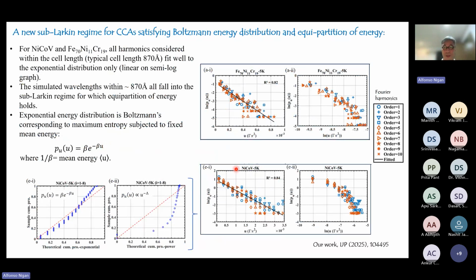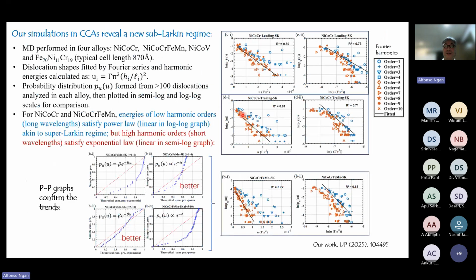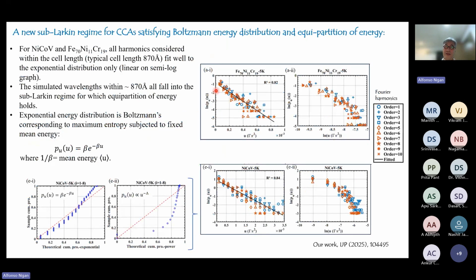And this graph shows the remaining alloys that we have looked at. So these two are that one and that one. For these two alloys, within the length of the simulation cell, we only see the Boltzmann distribution. We only see the linear behavior in the semi-log. If you plot the data in double log, the data would exhibit obvious curvature. So all the data, from low to high harmonic orders, so long wavelengths to short wavelengths, within the simulation cell length, we only see the exponential distribution, which is linear in the semi-log.